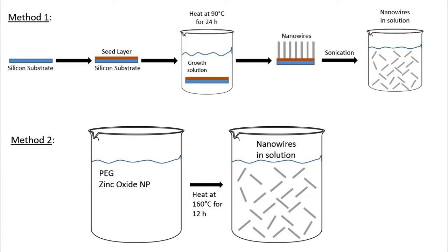The first methodology studied in my analysis is the traditional growth method that has been studied at LMGP for several years. This method involves cutting a small square silicon wafer substrate and spin coating that with a zinc oxide seed layer. This sample is then submerged in a growth solution at 90 degrees Celsius for 24 hours. In this time, the nanowires grow on top of the substrate and seed layer. Once the growth is complete, the nanowires need to be cut from the sample using sonication. Finally, the nanowires are resuspended in solution where they can later be filtrated to form a membrane.